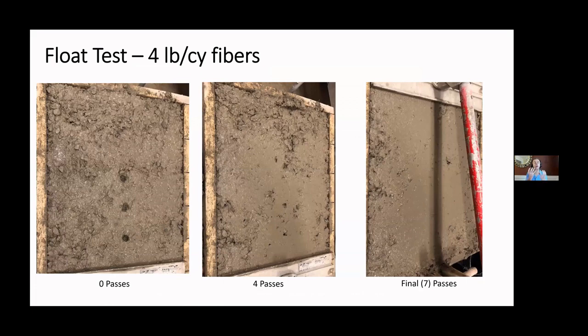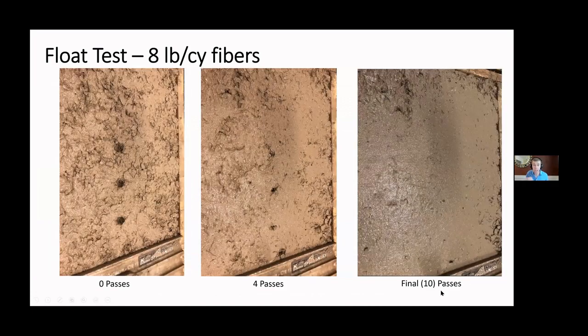So again, we can start to see how these fibers work. Here's 4 pounds per cubic yard, which is a pretty low dosage of fibers. This is what it starts out at. Here's 4 passes. Here's 7 passes, just a little bit more finishing needed with this fiber. If we go up to 8 pounds, a lot of people say more is better as far as fibers go, but look at this. It took 10 passes to finally get that concrete to close up. And you can see it still has a few issues in it. That's not good. That's not a baby aspirin.